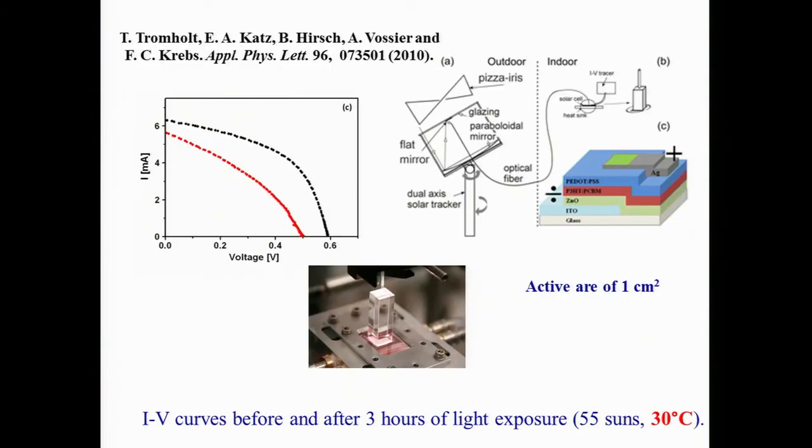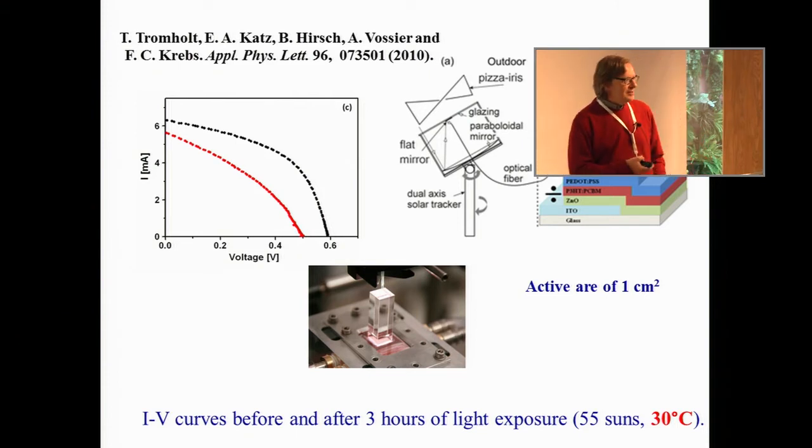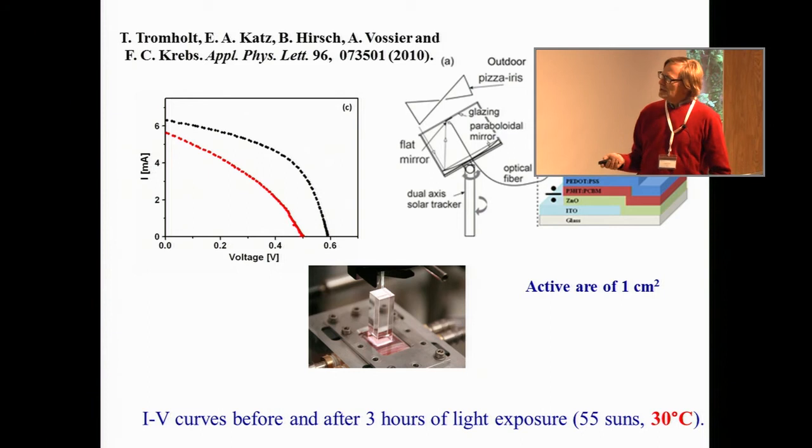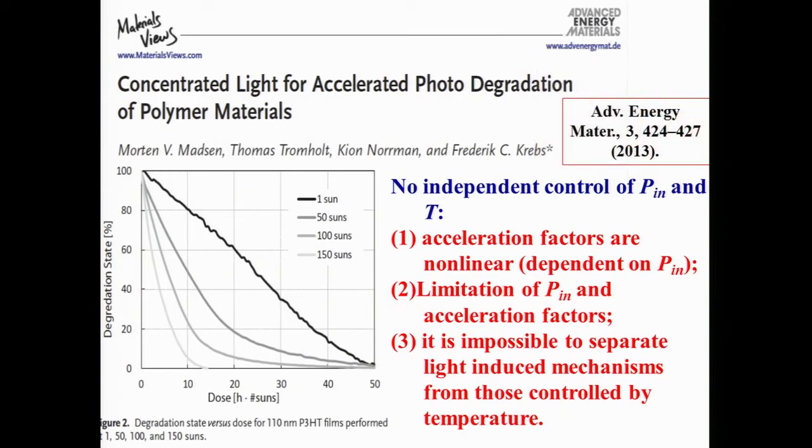When we tried to cool the cell, we saw that the degradation is not so crucial. It's a small degradation in all parameters. So at that time we were very optimistic that we could separate the light-induced mechanism of degradation and the temperature-induced mechanism of degradation, so we can do many things with such methods. And Frederik today in the morning showed us their beautiful concentrators with sunlight and with solar simulator. They published a paper in Advanced Energy Materials last year showing a very interesting result.